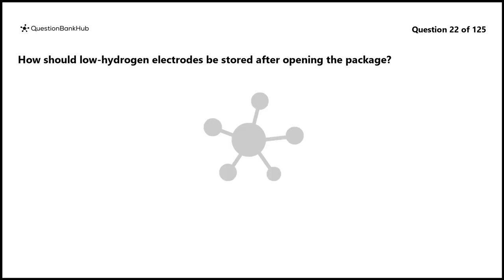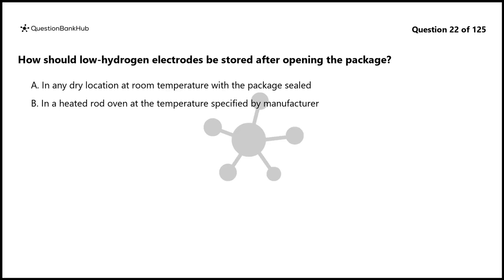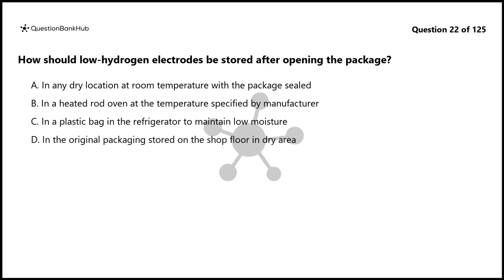Question 22. How should low hydrogen electrodes be stored after opening the package? A. In any dry location at room temperature with the package sealed. B. In a heated rod oven at the temperature specified by manufacturer. C. In a plastic bag in the refrigerator to maintain low moisture. D. In the original packaging stored on the shop floor in dry area.